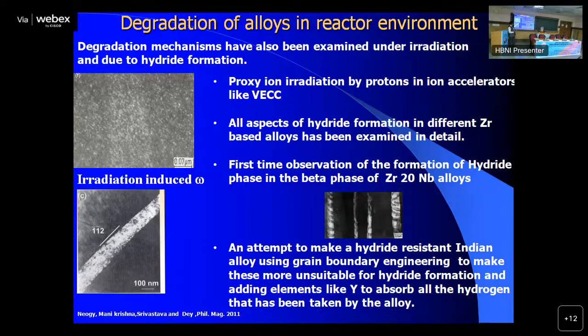All that knowledge bank has been developed, and that is very useful when it's actually called to solve a problem by NPCIL colleagues when a certain type of failure has taken place. One particular observation which I would like to show, this is the first time in the world where we showed that the beta phase also can have hydride formation. Earlier it was shown that hydrides can form only in alpha phase, but we showed for the first time that hydride can form in beta phase also.